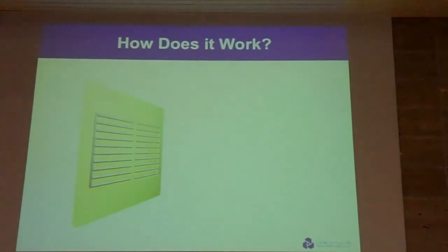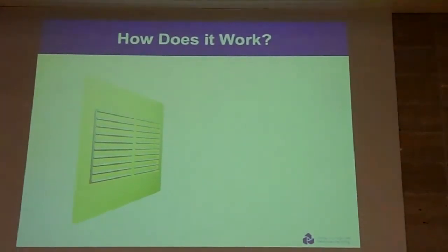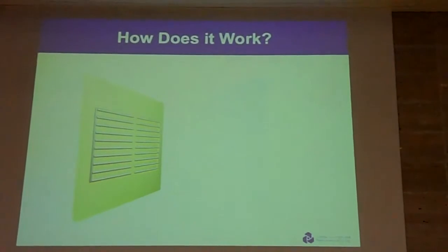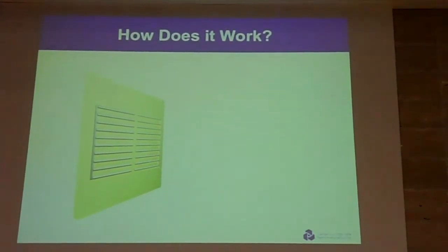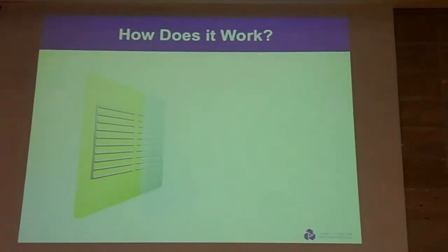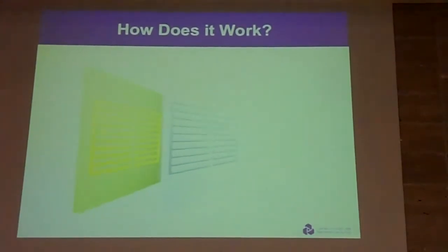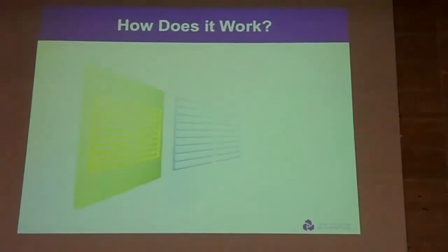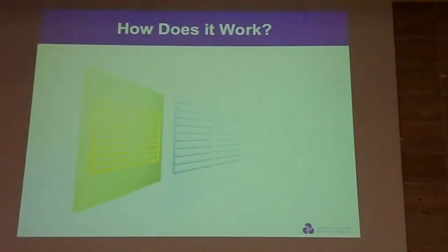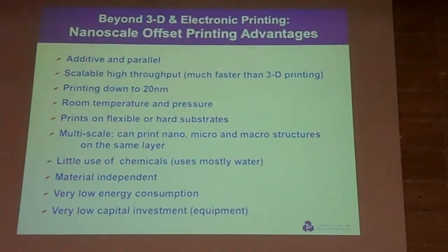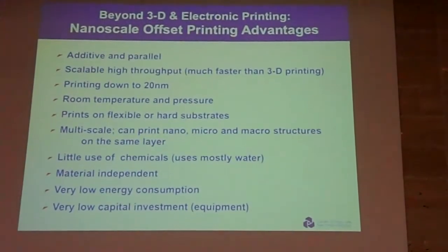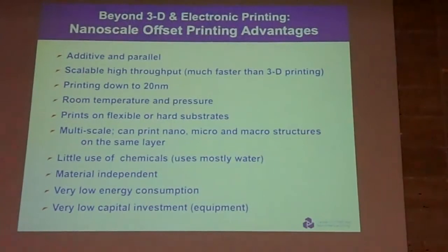And it takes 1 minute. It doesn't matter if you're using a template this big or a template this big. It takes 1 minute. And then once you finish, you transfer whatever you made onto another substrate, and then use the template again. It's just like printing. Very similar. So when you use this process, what does it mean? Well, first it's additive. That means we don't do etching, we don't remove any material, we only add material.